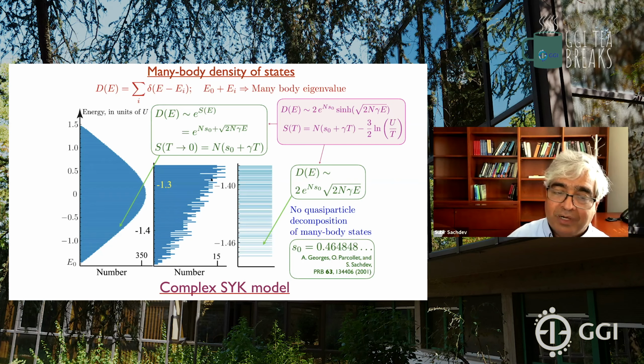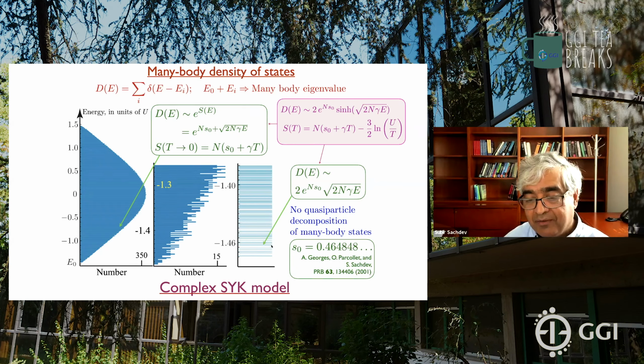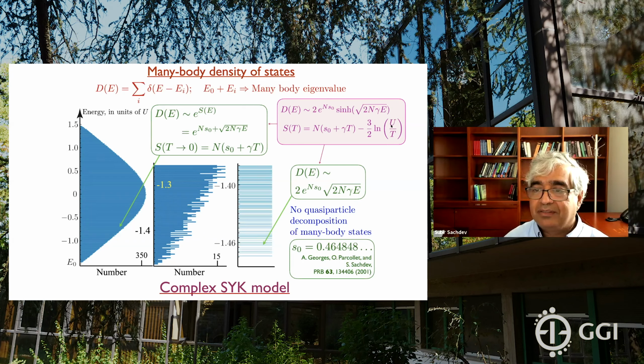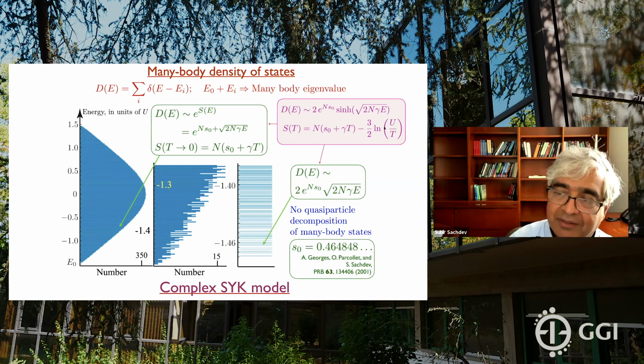So the bottom line is, if you take one SYK model for sufficiently large N and you numerically compute the density of states on all the energy levels, you will get these very discrete levels. They're very hard to characterize, but you get some continuum density of states, I mean, some very dense set of levels, all discrete. Now, if you do a little bit of coarse graining and average them, you will get some function, this function here, in fact. And this has been numerically checked. Then from this function, once you have the density of states, you can compute the entropy as a function of temperature by a Laplace transform. You'll get this answer, and this is, in fact, the entropy of a generic charged black hole at low temperature.